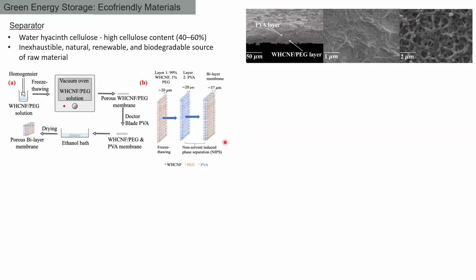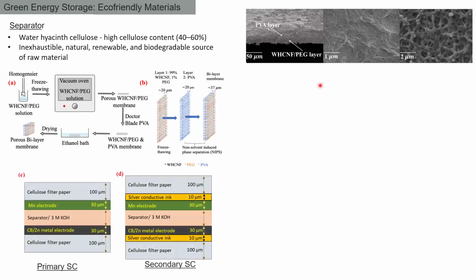And then, as you can see from here, there is a double layer formation of this material, and this type of material we implemented for a primary supercapacitor or a secondary supercapacitor electrode. In a primary supercapacitor, the electrode is fabricated on a paper-based electrochemical capacitor, where we deposited a manganese electrode on paper, then the separator with potassium hydroxide as an electrolyte, and another separator. It's like a hybrid supercapacitor.